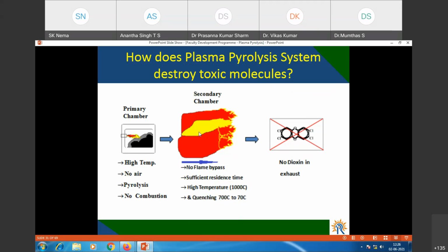Then in the secondary chamber, we maintain a long plume, and whatever combustible gases are forming are also helping in the secondary chamber. You are getting a long plume in the secondary chamber, and you are able to maintain high temperature. So this high temperature again takes care of the complete disposal of the waste, and gases are converted into carbon dioxide and water vapors. After this, immediately we go for quenching. From 700 degrees centigrade, gases are quenched to 70 degrees centigrade. So that is again taken care of, so that you can completely avoid recombination reactions, and therefore such toxic things do not form.